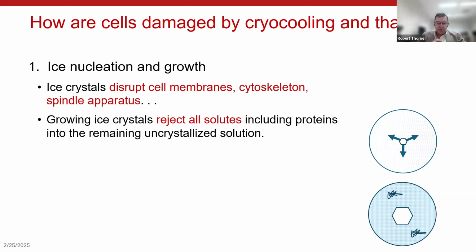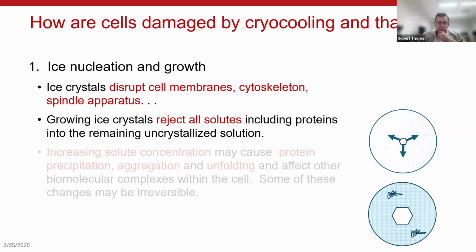Another key thing is a chemical effect, and that results because ice crystals are essentially pure water, and as they grow, they reject essentially all solutes from the cytosol. And so those solutes become concentrated in the remaining uncrystallized solution. And that includes salts, proteins, I mean, everything but water will get concentrated.